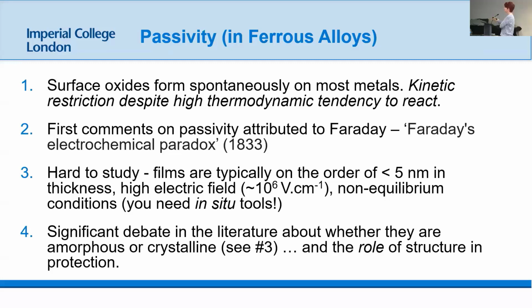And passivity, like most things in electrochemistry, was first really recorded and commented on by Faraday. This is known as Faraday's electrochemical paradox. And in contrast to what Bill was saying earlier, what Faraday noticed was, as you go to a high concentration solution of nitric acid, your iron stopped corroding. Right? And that's got to do with a huge oxidation potential, which allowed it to passivate, that you got with the concentration of the acid. And Faraday noticed this, despite being 70 years before the pH scale was invented, and before we really understood what surfaces were and surface oxidation was.